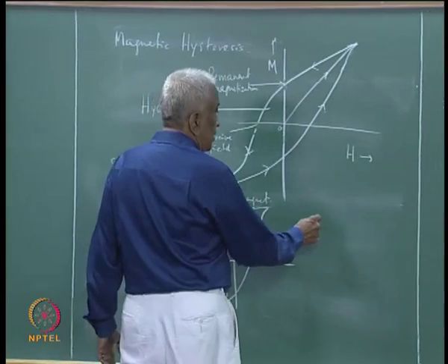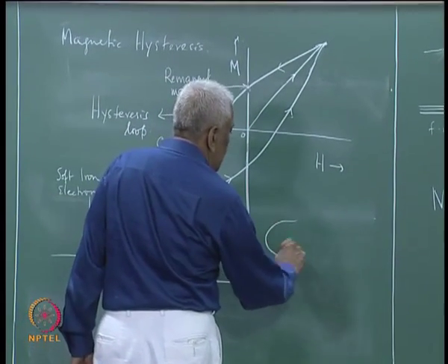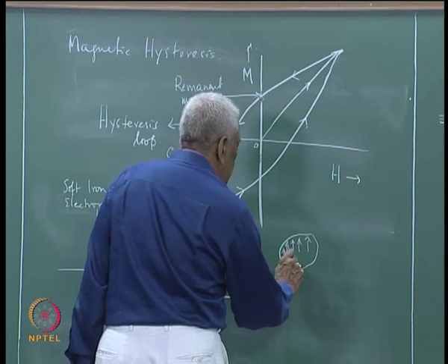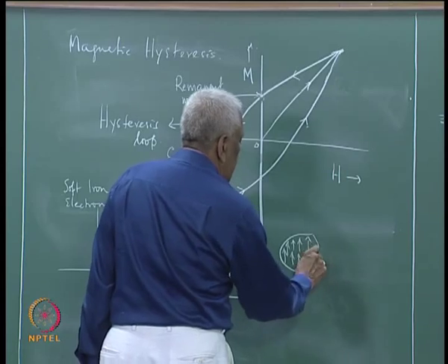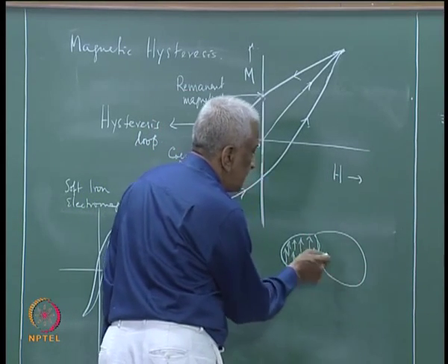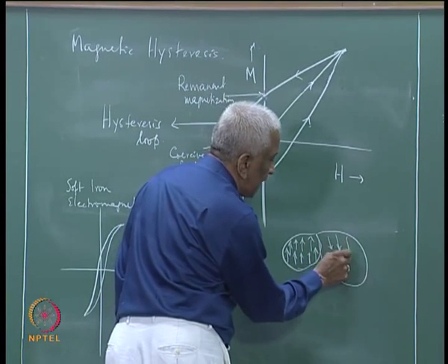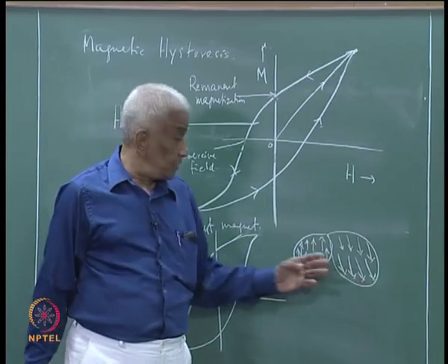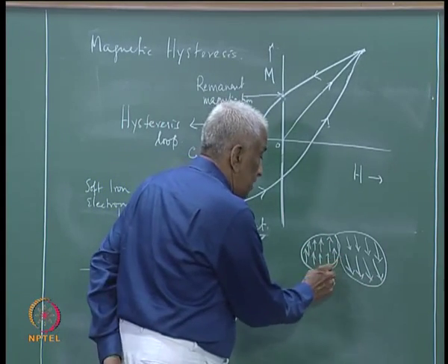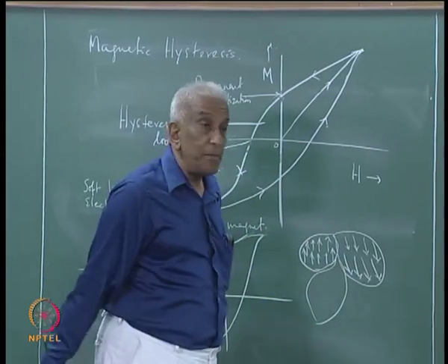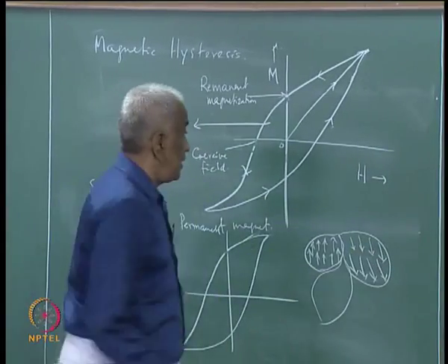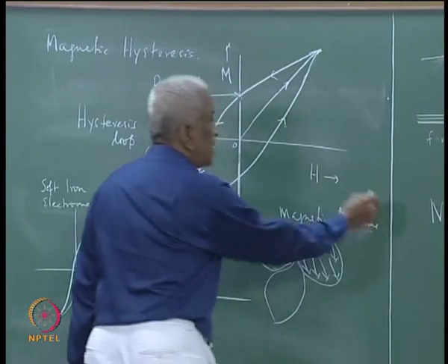The behavior of a ferromagnet or any ordered magnetic solid is such that there are domains inside, in which, for example, in a ferromagnet there is parallel alignment of the spins. And then there is another neighboring magnetic domain in which this may be completely different, but still parallel. So within a domain the alignment is parallel, but in neighboring domains the alignment is not necessarily parallel. On the whole you have a large number of magnetic domains within which there is ferromagnetic parallel spin alignment, but between which there is no correlation.